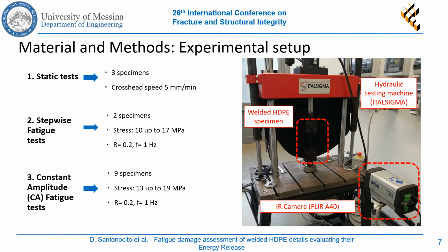Three kinds of tests were performed. Static tensile tests on 3 specimens adopting a crosshead speed of 5 mm per minute. Stepwise fatigue tests applying the thermographic method on 2 specimens with stress levels from 10 up to 17 MPa with a stress ratio of 0.2 and test frequency of 1 Hz. Constant amplitude fatigue tests in order to obtain the SN curve of the material on 9 specimens with the same stress ratio and frequency of the stepwise test.